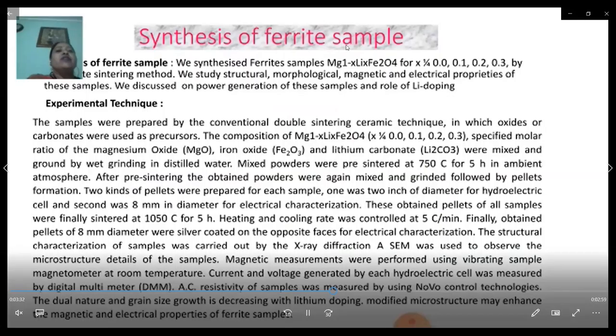The sample was prepared by the conventional double sintering ceramic technique, in which oxides and carbonates were used as precursors, and the compositions of this MgLiFe2O4 specified molar ratio of magnesium oxide, iron oxide, and lithium carbonate that were mixed and ground by wet grinding in distilled water. Mixed powder was sintered at 750 Celsius for 5 hours in air atmosphere. After pre-sintering, the obtained powder was again mixed and ground, followed by pellet formation. Two kinds of pellets were prepared. One was 2-inch diameter for the hydroelectric cell and second 8 mm in diameter for electrical characterization.